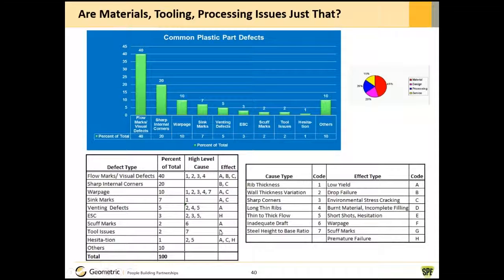But more than likely, it's caused by 1, 2, 3, 4, and 7, which is rib thickness, wall thickness variation, sharp corners, long thin ribs, and steel height to base ratio. All of these can cause warpage. So don't assume that warpage is due to processing. Ultimately, most of these issues that we classify as tooling, material, processing, a lot of them can be traced back into design. And you as a designer are responsible for it.